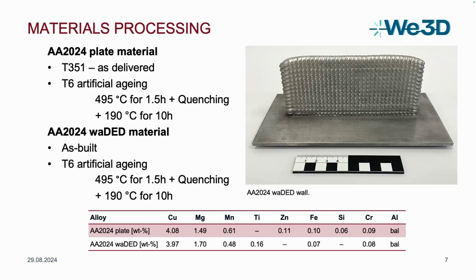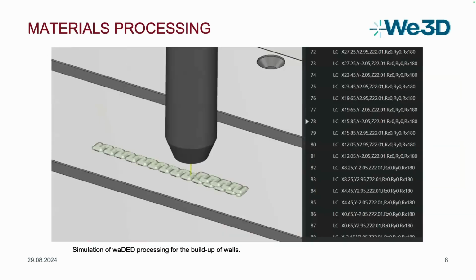Furthermore, here in the table, we can see the chemical compositions of the materials, so the plate material and the wire arc DED material. Basically, we have copper, magnesium, and manganese in it, with one major difference: we have also titanium in the wire arc DED material as the grain refining element.